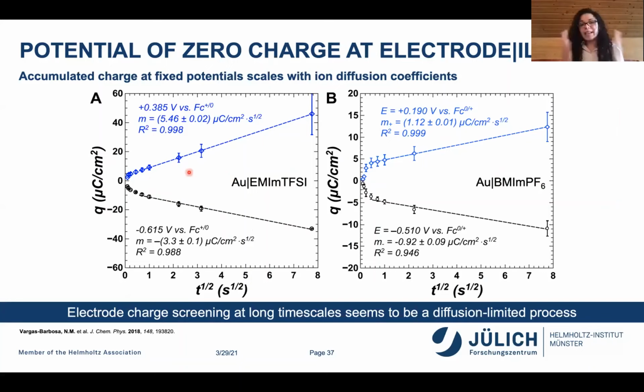And what we could take at the time from that is that the electrode charge screening at long time scales seems to be a diffusion limited process. It actually seemed to correlate with the diffusion coefficients of the ions themselves in the ionic liquid. And so we still don't have a full explanation as to why this is the case. But had we not done the impedance analysis, we would have never reached this level of insight.